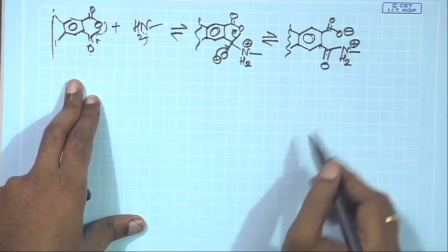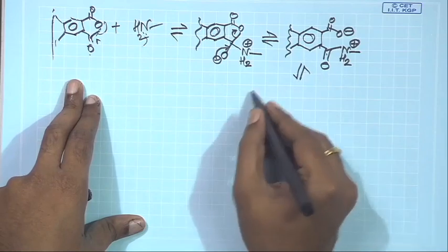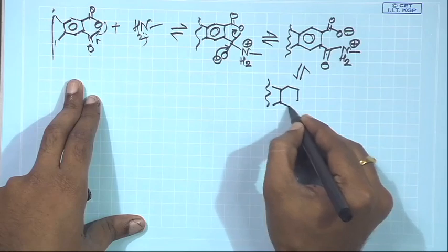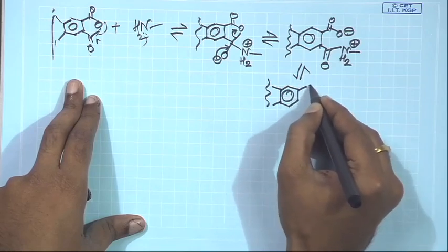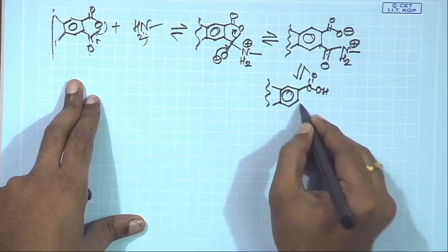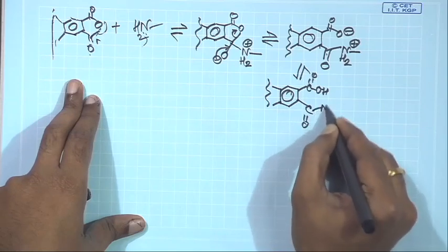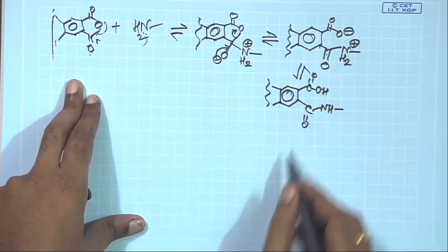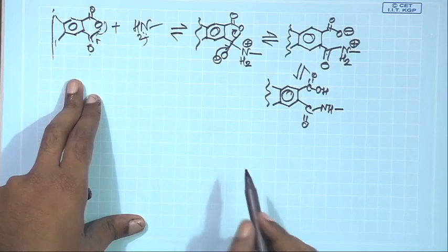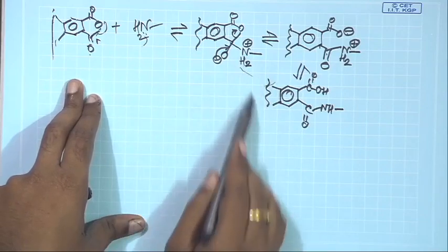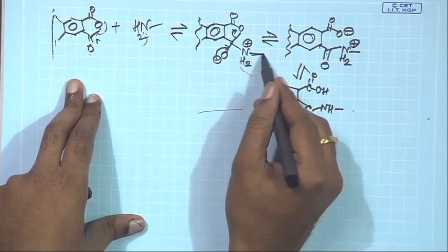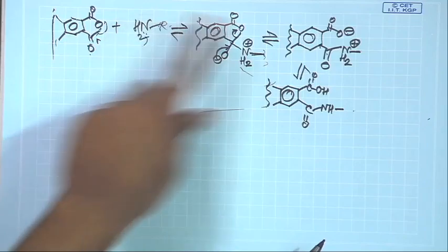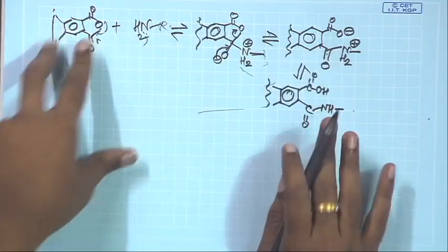Again I am not drawing the carbon here, and then in the final step there is a simple proton exchange, this proton goes here. So, it takes care of these charges. So, what you will have here basically is COOH and CONH2, actually NH this. So, you have the long chain. So, this is your polyamic acid. On this side also you will have a carboxylic acid like this, and you have a chain that is going on. Okay. So, this chain is going on here, R NH2 is there. So, this chain is going on. So, this is your polyamic acid synthesis in a nutshell, the mechanistic aspects.